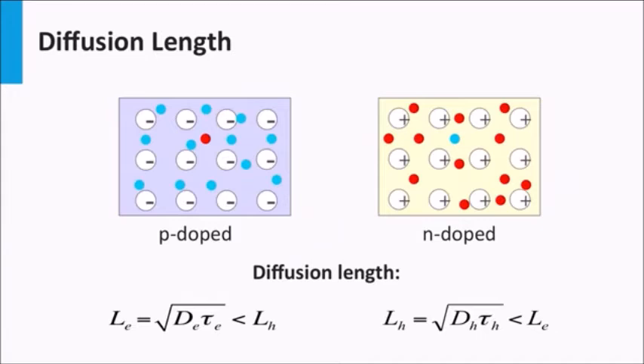The recombination mechanism, as we have discussed last week, also affects the diffusion length of the minority charge carrier. The diffusion length is given by the simple equation L, which is the square root of the diffusion coefficient D times the lifetime tau of the minority charge carrier. This leads to one additional limitation of the solar cell design. The absorber layer of a solar cell cannot be thicker than the typical diffusion length. Why is that the case?